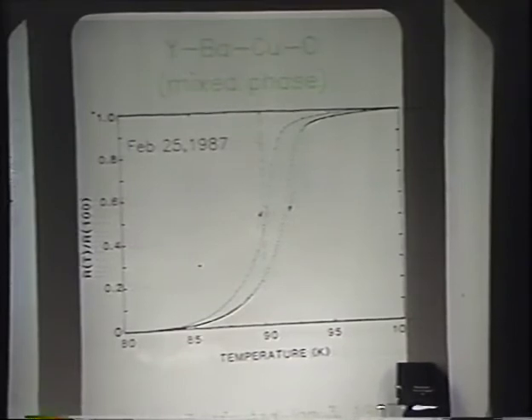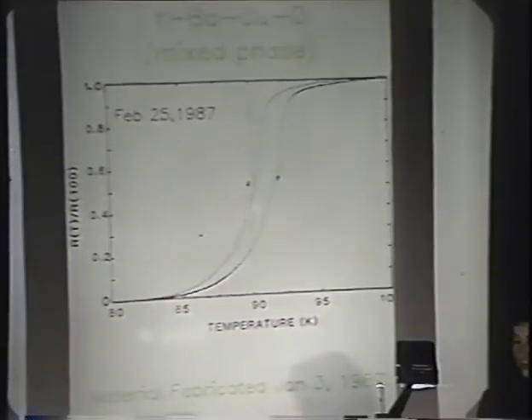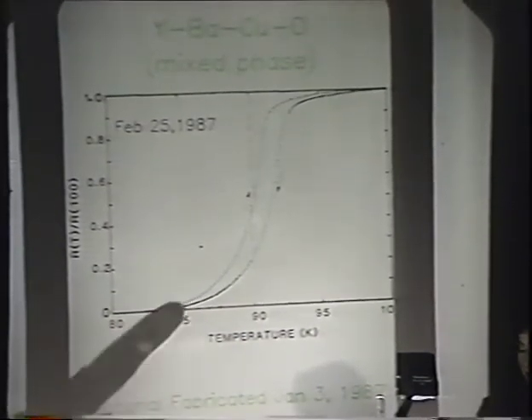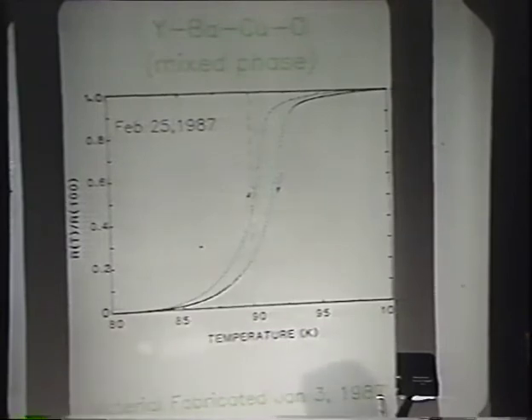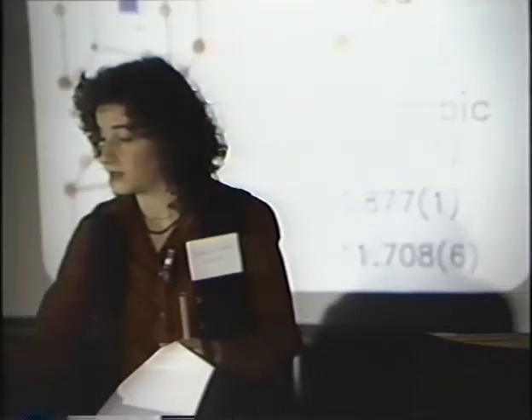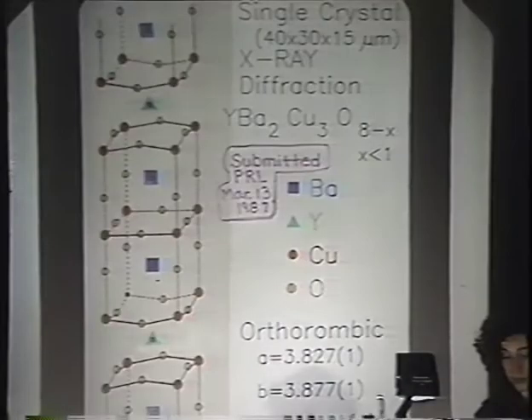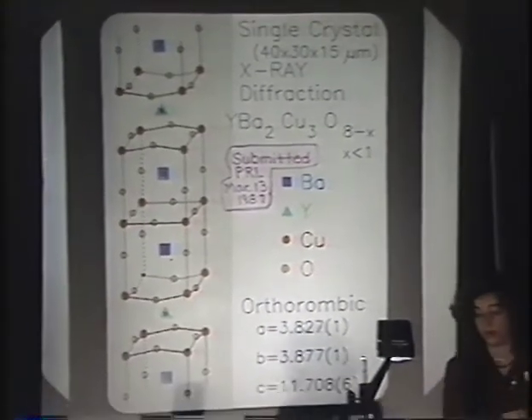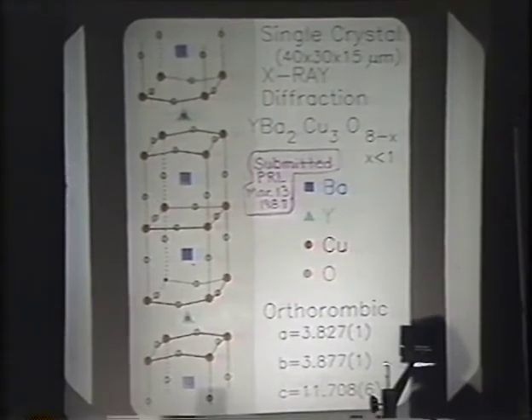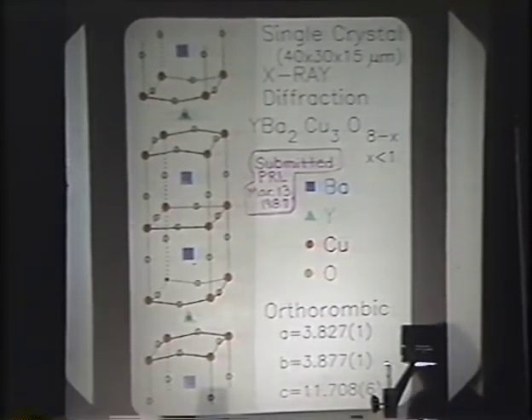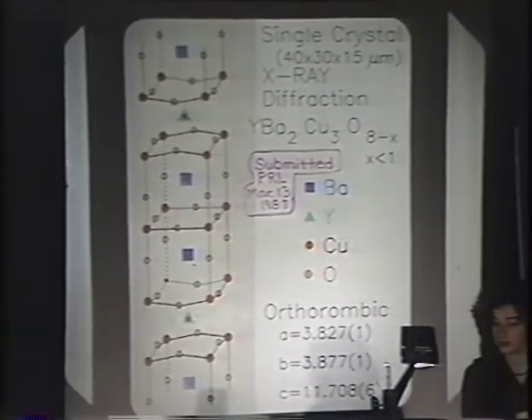For historical reasons, this is our first yttrium barium copper oxide material, measured in February. The material was fabricated on January 3, 1987. I'd like to point out that this also has a typical resistive midpoint of about 91 degrees. Since then, we've isolated the phase and grown single crystals, and the results of the single crystal X-ray diffraction are presented here. This was done on a 40 by 30 by 15 micron crystal. We now have significantly larger single crystals, in the millimeter range.